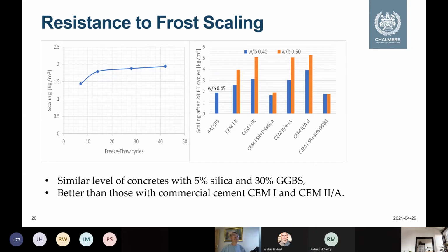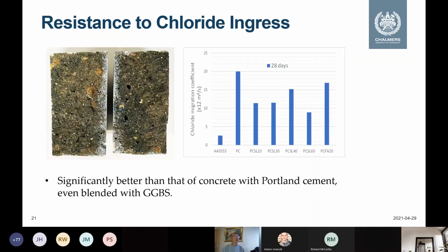So you can see that in fact this alkali-activated concrete, the scaling is in the range of ordinary Portland cement without air entraining. So 0.4 to 0.5, you can see that it is in a similar range, even for the pure cement concrete. So in fact, it is not so bad. It is just similar.